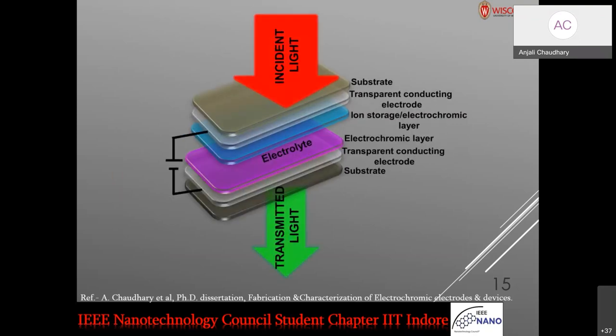And this is a typical structure of an electrochromic device. You take two conducting electrodes, and these are substrate. Over there is a transparent conducting electrode, which is usually ITO or FTO, indium tin oxide or fluorine-doped tin oxide. And over there is the electrochromic layer, which is this here, and on the other electrode you have an ion storage or electrochromic layer, and in between both of them there is an electrolyte which helps in conduction or movement of ions.